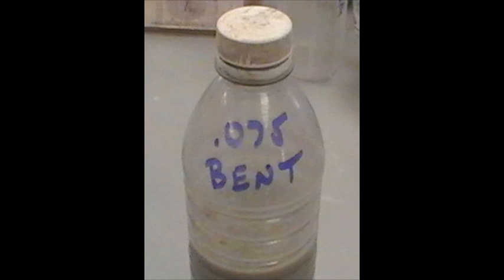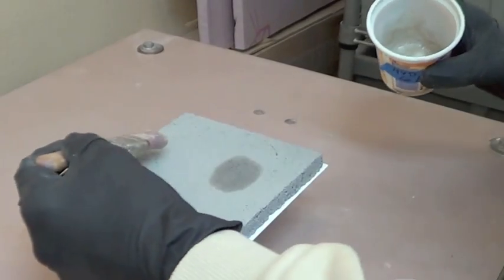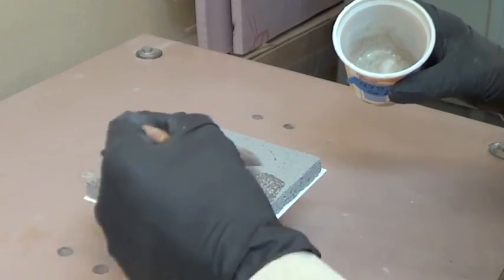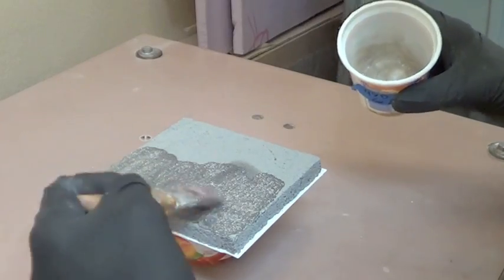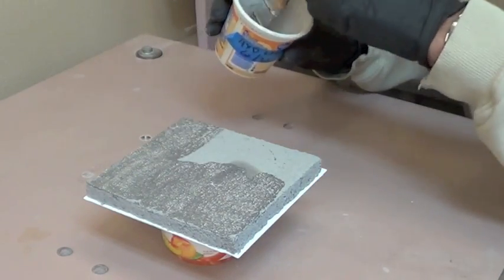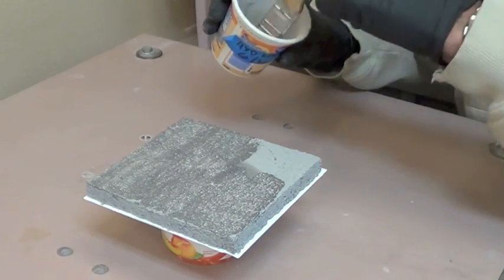When the clay is dry, coat it with a mixture of sodium carbonate — also called soda ash — and bentonite clay mixed in water. I use a water mixture with 7.5% bentonite clay by weight. For this 5x5 tile, I mix 4 grams of soda ash and 10 grams of the bentonite clay water solution. Bentonite and soda ash can be purchased at ceramic supply stores. Brush the salt solution onto the tile. The clay won't dissolve in the solution because it's too rich of a mixture — that's okay, just spread it as evenly as you can.